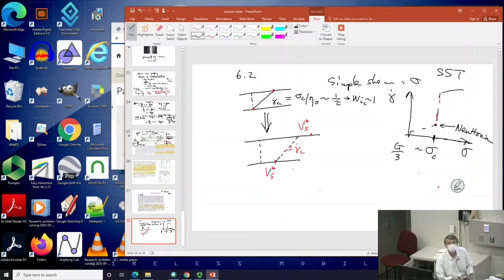Alex, you have a question. I think you're touching many points. First of all, I claim that for monodispersed sample, this point is Newtonian. Secondly, let me rephrase the question a little bit. Suppose, it's a wonderful question, suppose it's not monodispersed. I told you not being monodispersed has just a tiny confusion, not too much. What does it mean not being monodispersed? Let me first say, when it's monodispersed, the relationship between them is a double log, slope of one. That's Newtonian viscosity. Let me give you a scenario where it's not Newtonian.